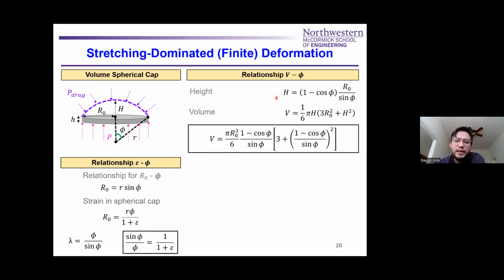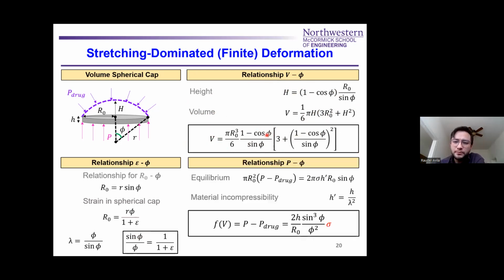And then we can derive our relationship for the volume based on the geometrical features of the spherical cap. So we can find what the height is going to be as a function of phi, and then also what the volume is going to be as a function of phi based on the height of the membrane. And we find this relationship right here. We have volume on one side of the equation, and phi on the other side. All of these terms only depend on phi, so this only evolves as you're increasing your angle phi.